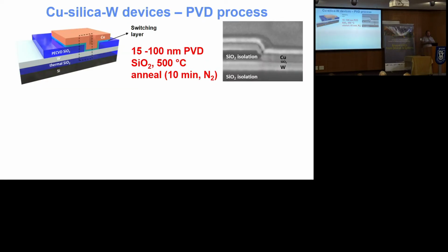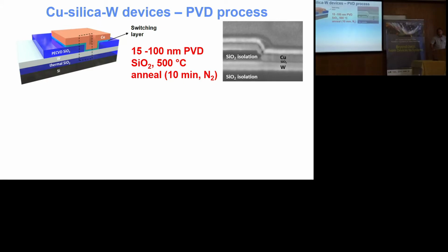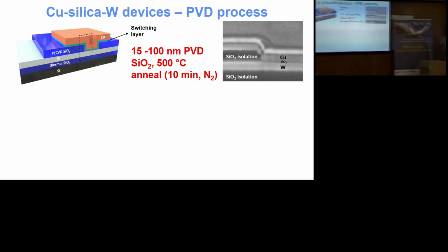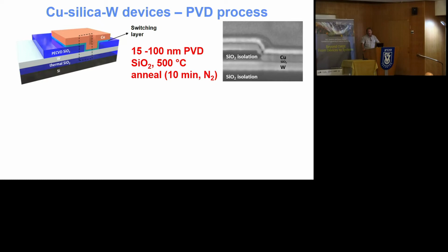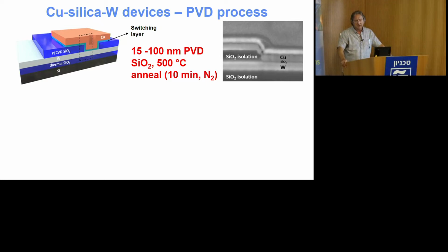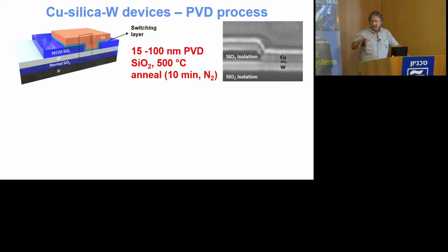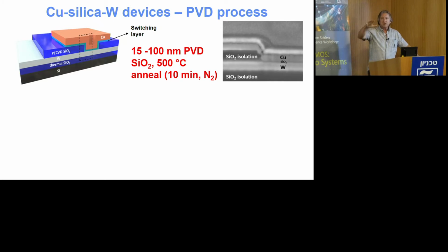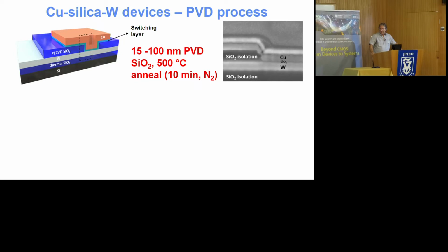So what do these things look like? Well, very, very simple. Just that kind of sandwich that I showed you before: copper top electrode, a silica, porous silica, I should say, switching layer, and then a conducting bottom electrode, tungsten, say. We can deposit that oxide by PVD, or, as I'll show you in a second, CVD. We can pre-dope it using thermal diffusion of the copper into the oxide, which takes several hundred degrees C, typically 500-odd degrees C, which a lot of people aren't 100% happy with in back-end-of-line, but it is one way of pre-doping the oxides, which, in essence, allows you to reduce the forming voltage that you have to use in order to get these things to switch in the first place.